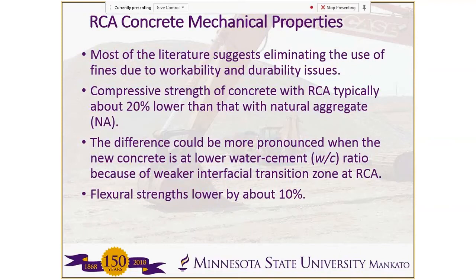Okay, so the mechanical properties of recycled concrete aggregate have a huge part to play in the performance of that concrete. Most of the literature suggests that you don't use the fines, the recycled aggregate fine material, because that causes a lot of workability issues and some durability issues with the concrete. Compressive strength of concrete using recycled aggregate is typically reported in the literature to be about 20% lower than if you used a natural aggregate. But if you're using a lower water cement ratio, the difference might be even more pronounced.